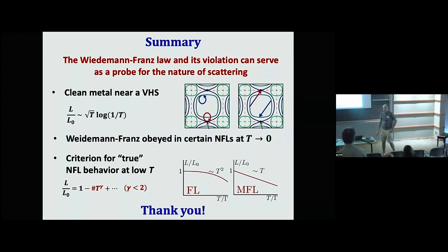So in Abrikosov's textbook on the theory of metals, there is a beautiful line that says the Wiedemann-Franz law is a law of nature if ultimately heat and charge are carried by one and the same entity, which is the electron. As long as this is true, the T equal to zero limit will be obeyed. Either you must have other entities that would be on a par with electrons, or it will not be obeyed.